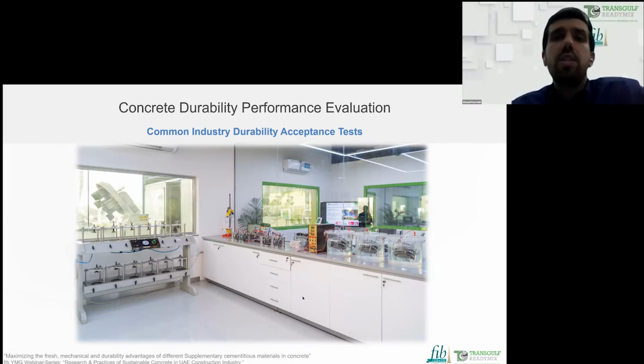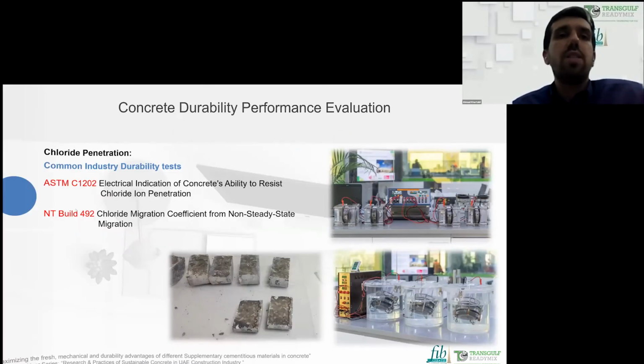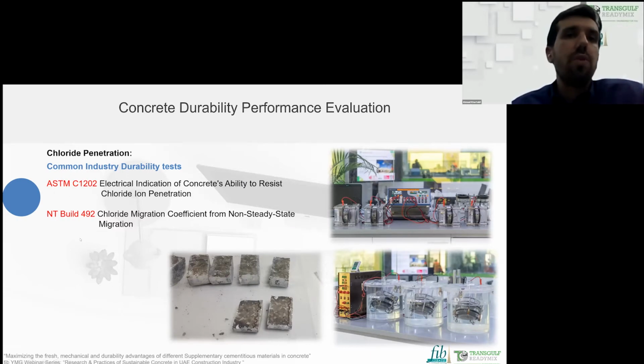Generally, this is a picture from our laboratory, in which we do in-house testing for all the durability tests, like rapid chloride penetration, chloride migration, water permeability, water absorption, and some other tests as well. I mention here the general standard for the rapid chloride penetration is ASTM C1202, and for the chloride migration, NT Build 492.